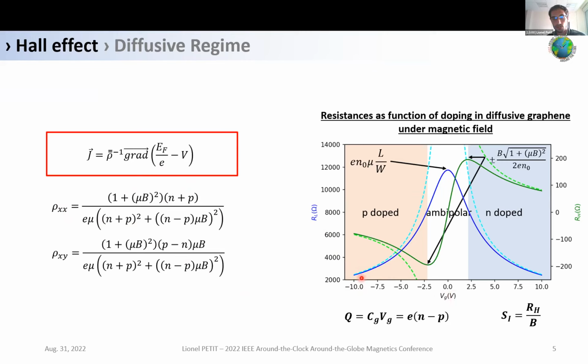So here you can see the blue curve, it's the longitudinal resistance, and it's a Lorentzian, which is typical of graphene, and its maximum corresponds to what we call the charge neutrality point. It corresponds to a point where the Fermi level lies exactly at the tip of the Dirac cones.